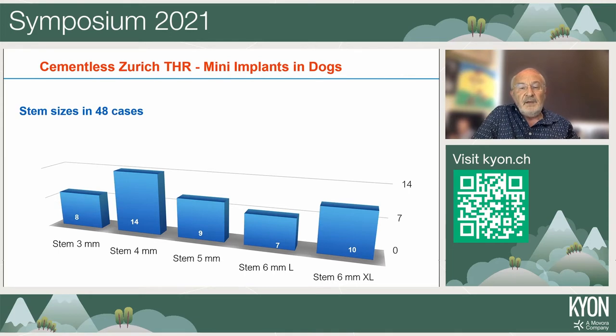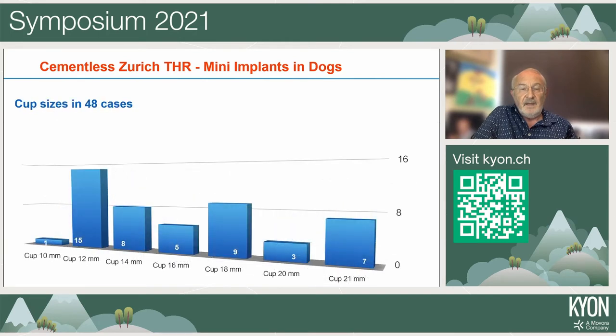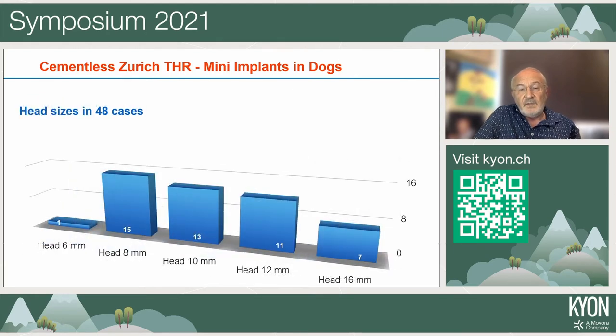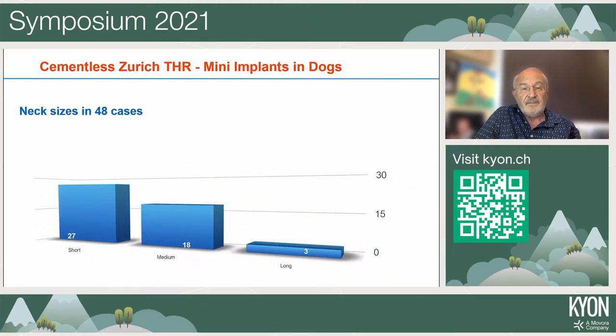About the implants, I use almost all the implants available. The most common I used was the 4 millimeter stem, and also the 6 millimeter in bigger small dogs. About the cup, the most commonly used was the 12 millimeter because it is common for small breed dogs like a Jack Russell or Yorkshire and so on. But we use also other sizes. And about the head size, the 8 millimeter and the 10 millimeter are the most commonly used.